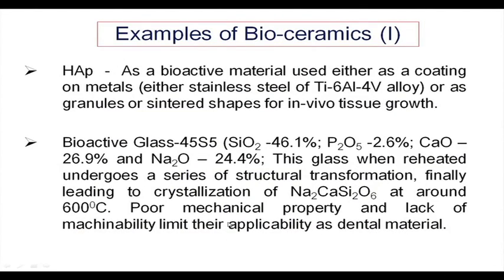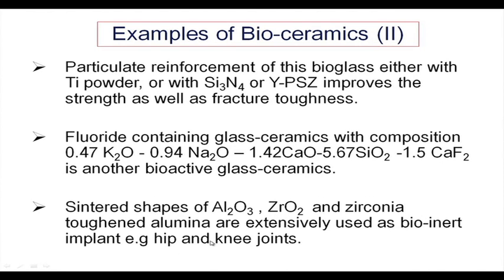Relatively poor mechanical property. It is not an absolutely useless material, it is a very useful material, but it has relatively poor mechanical property and lack of machinability. That is true for most of the glasses and ceramics, but there are machinable glass ceramics also. Some of it is used in dental implants, and there, because of complex shapes, machinability is an important consideration. Particulate reinforcement of this bioglass with titanium powder, because mechanical property is relatively low.